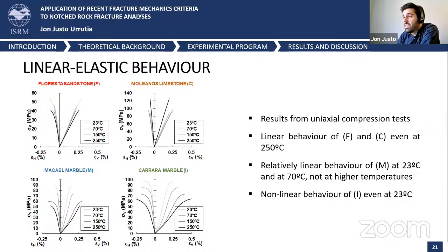Here we have some representative stress strain curves obtained from the uniaxial compression test for each of the 4 selected rocks. They offer a clear view of the linearity of their behavior, even at different temperatures. The Floresta sandstone and the Moleanos limestone present a very linear behavior even at 250 Celsius degrees.